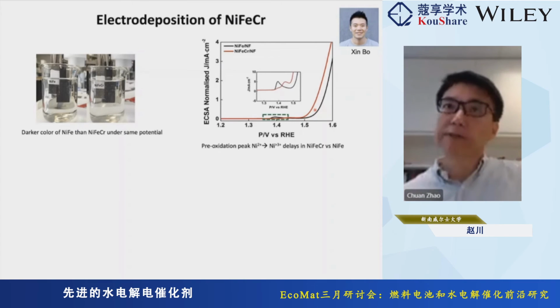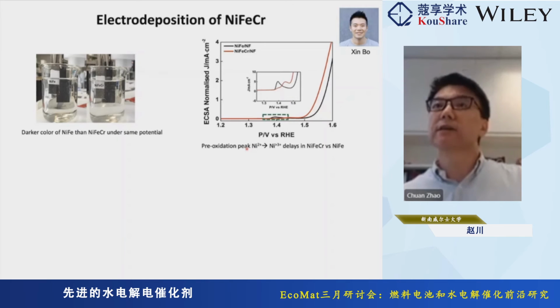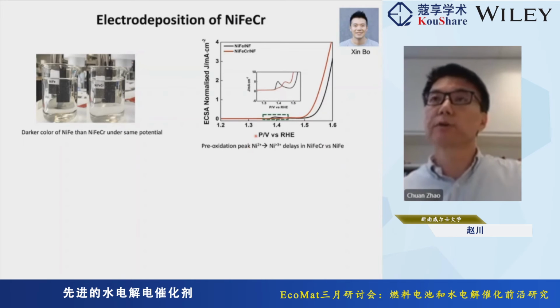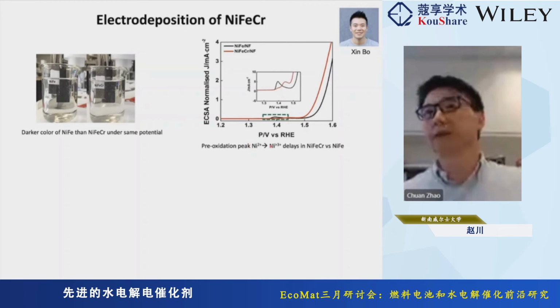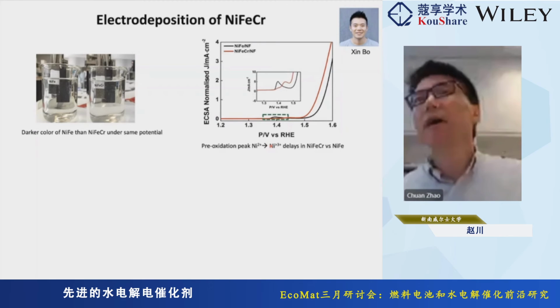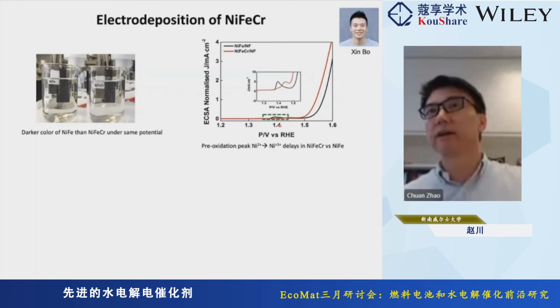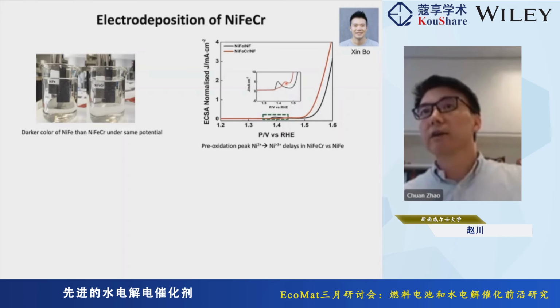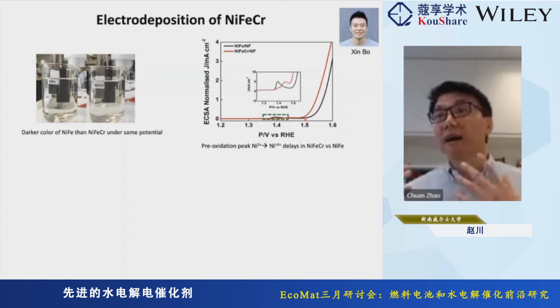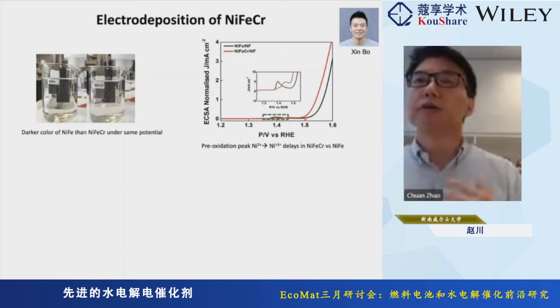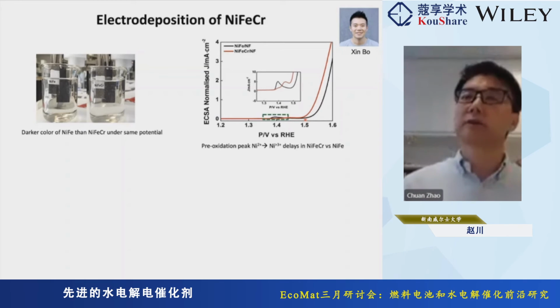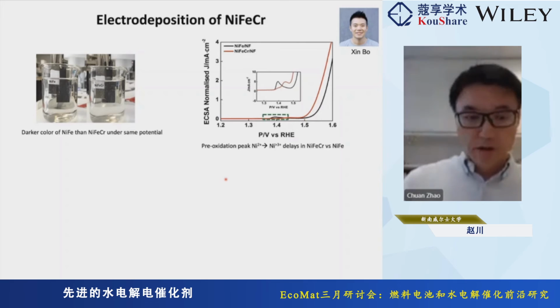When we look at this pre-oxidation peak here, that is often attributed to the oxidation of nickel 2+ to a higher oxidation state. What we noticed is that there was a delay in the oxidation peak for the nickel iron chromium. So just adding chromium actually adjusts the redox chemistry of the surface as well.